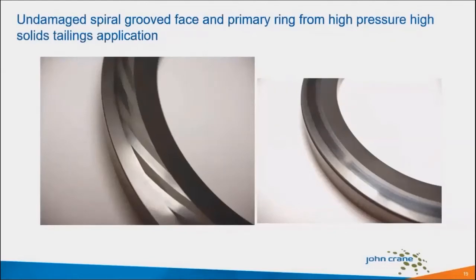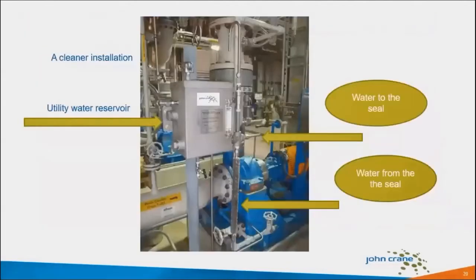So we deliver that water through a very simple system. The next slide shows a very simple water delivery system. This is one that is completely unpressurized. So we're just operating on the head pressure of that stainless steel box full of water, which feeds the seal. And the seal uses that low pressure water. The grooves pump it to a much higher pressure into the process. So as the grooves rotate, they create their own pressure. This is a very simple system.